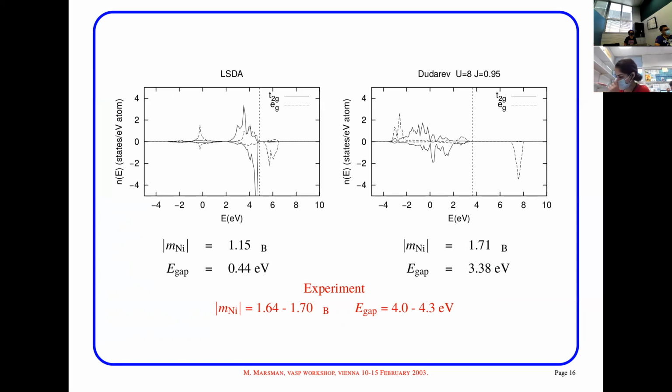And if you see, for instance, that you get a band gap that is like 1/6 of the value that you expect, then a bell should ring in your brain: here I need to apply the Dudarev approach, because otherwise I am mimicking things that are not physical. And then you apply the Dudarev approach.